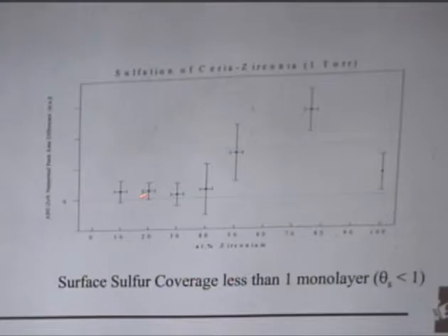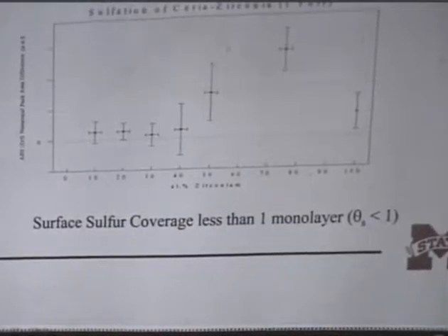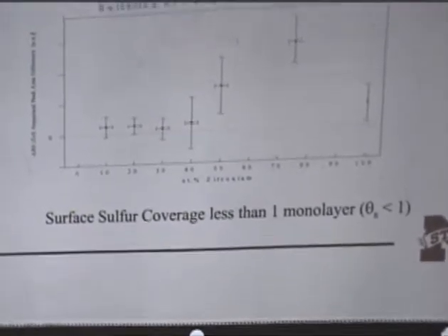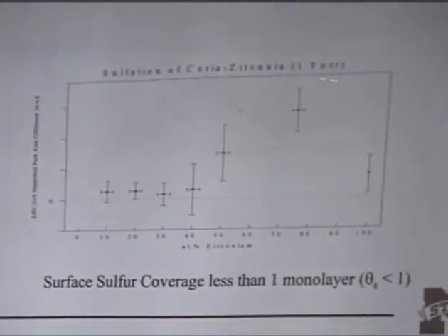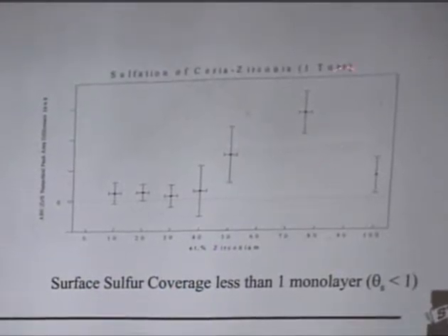Okay, we see a little bit go down, then we see this maximum out here at, we'll say, 80% zirconium or so. We believe that this is due to the fact that we're seeing additional oxygen vacancies at this particular set of experimental conditions, so that if SO2 goes down, the first thing it looks for is a vacancy at very low coverages. This is not that hard to believe.